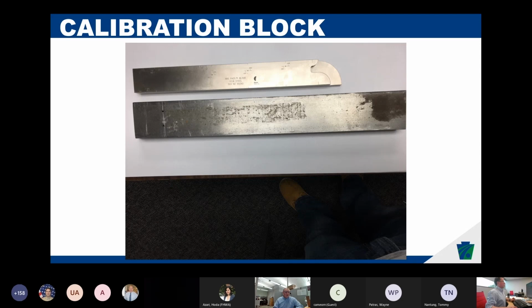Basically, what that means is we have to have a calibration block that can be calibrated over the full use of that sound path. Bridge steels, we have some pretty thick members, 2.5, 3 inches, 3.5 inches, which means we're no longer carrying around a 5 to 10 pound block. We now have to produce a 70-pound block that allows the full sound path, or calibration to the full sound path.